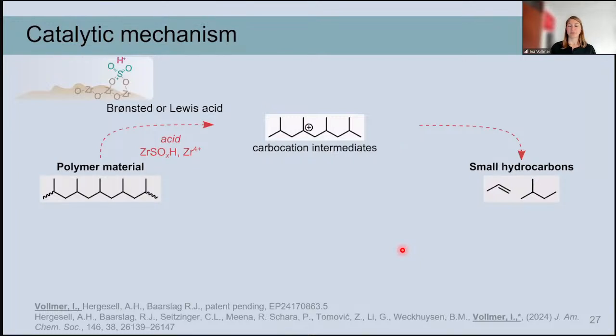But of course, we also want to understand a bit more deeply what the mechanism behind this catalysis is. And the initial idea, as I said, was to just imitate thermal catalysis and just to improve the contact between the polymer and the active site. And so in thermal catalysis, we have a Brønsted or a Lewis acid site, which then creates a carbocation intermediate on the polymer. And this can then further react to release small hydrocarbons.